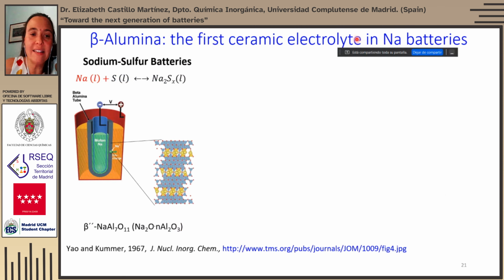Another strategy is to use ceramic electrolytes instead of polymers. We know that ceramics can also be good ionic conductors. And indeed, the first sodium-sulfur commercial battery, made by the Ford Motor Company in 1967, contained a ceramic beta alumina electrolyte, which transferred the sodium ions from a molten sodium tank to a molten sulfur tank. And this was at temperatures of 300 degrees.